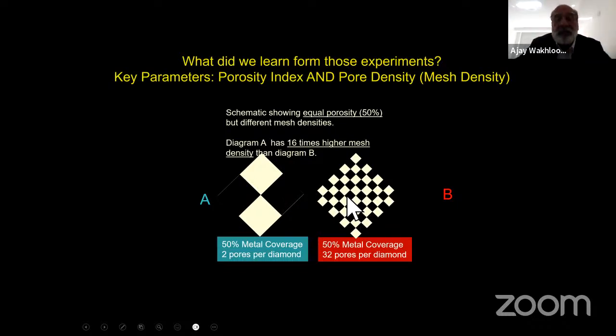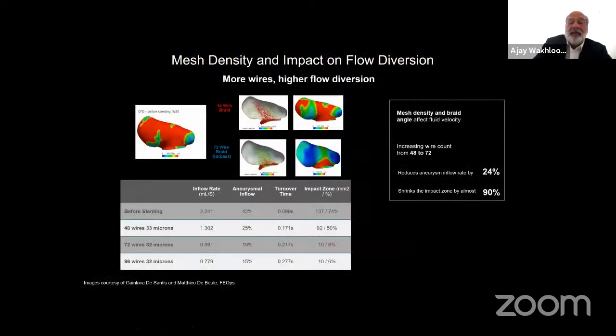How do we get from one to the other? By just reducing the size of the filament and increasing the number of the filaments. That has been proven also by this study from the Belgian group, De Beule, who took a 3D data set from a supraclinoid aneurysm and ran particles and computational work through this aneurysm. And what they found out is that in fact, adding number of the wires and increasing the mesh density has a higher impact on reduction of the flow exchange between parent vessel and the aneurysm. It has also, as expected, an impact on the shear forces experienced by the aneurysm itself.